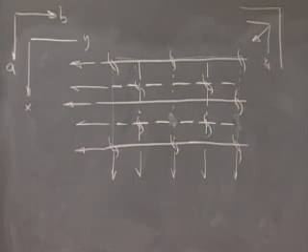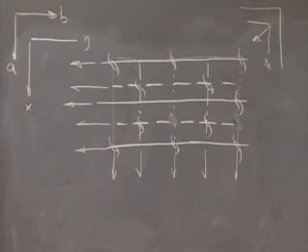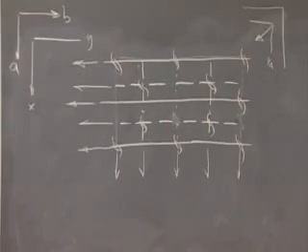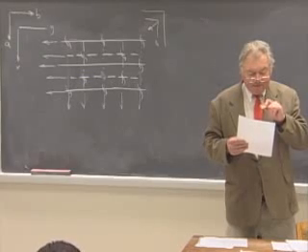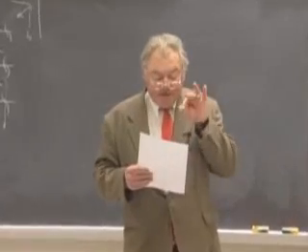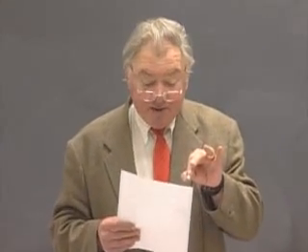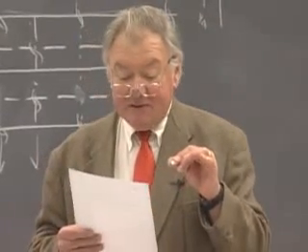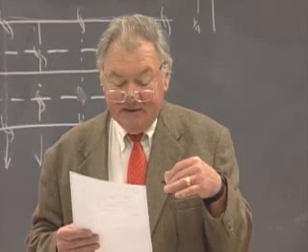Here for the first time we're seeing a complex space group that really requires the full range of symbols for representing the atomic locations. You will see for each circle a vertical line dividing it in half. These are two atoms then that are superposed in projection. One of them, corresponding to the little comma inside the circle, is the enantiomorph of those circles which are unadorned with that little comma, and they are therefore of opposite handedness.